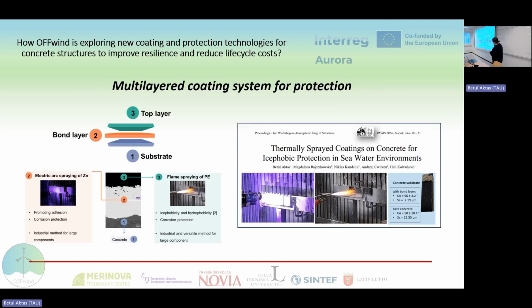And in this project a multi-layer structure coating system has been developed to get this protection. So if we think about this concrete as a substrate material, then we add a bond layer, in this case an electric arc sprayed zinc coating, which also gives that corrosion protection that is needed there in the seawater condition. Then we can apply on that a top layer, which is flame spray polyethylene coating here, and we can get this kind of multi-layer structure, which has multifunctional properties here.